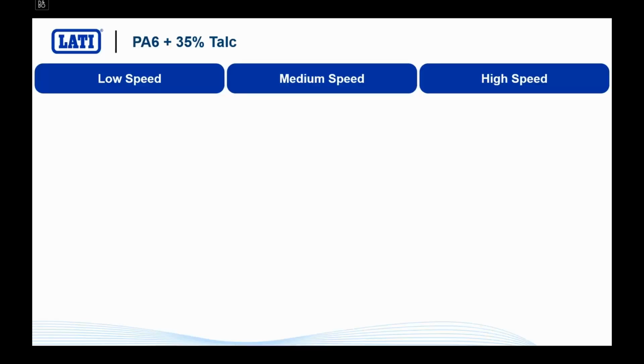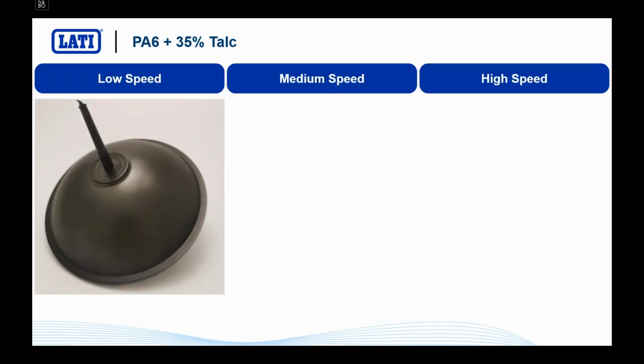Let's see what happens. Let's start from the very beginning. Let's start first material, polyamide 6, 35% talc, injected with 3 different speeds. First of all, with the fan gate. So with the fan gate, our bowl will look dull using a low injection speed. So you see that the quality of the surface is not really acceptable. It's dull, is slightly rough.